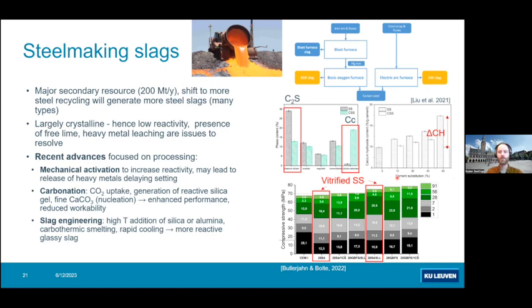And another interesting one is to do high temperature slag engineering, trying to modify the composition of the slag so that it becomes more suitable for application as an SCM, for instance, by reducing its iron content to make a composition which is more similar to blast furnace slag, to quench it instead of slowly cooling it to get a more reactive slag. And this is also what you can see in these results here, where you can see clearly, for instance, that vitrified steel slags can have really nice strength developments, even compared to CEM I in a 25% replacement. In combination with 5% of limestone, actually, one would be able to get higher strengths than the reference Portland cement.